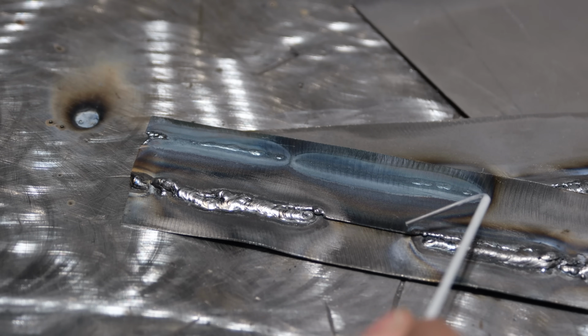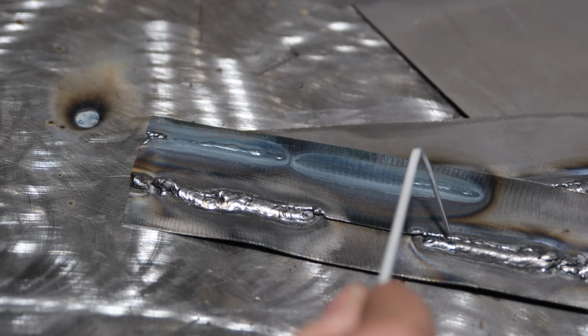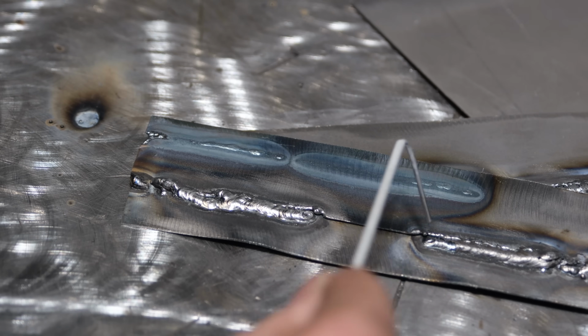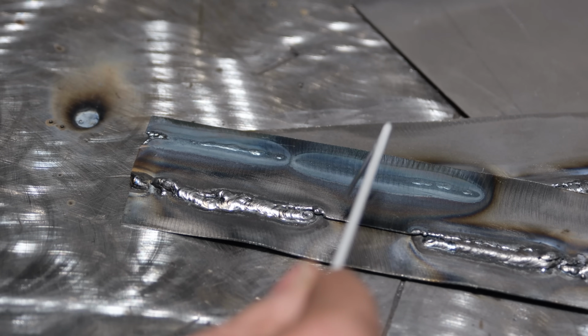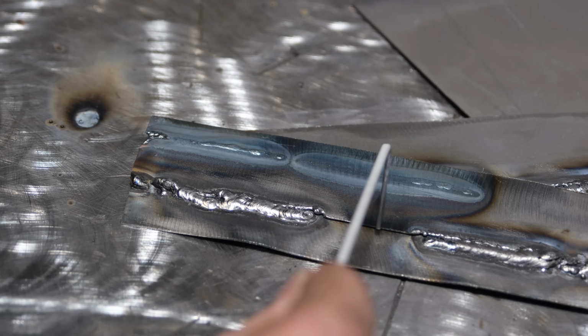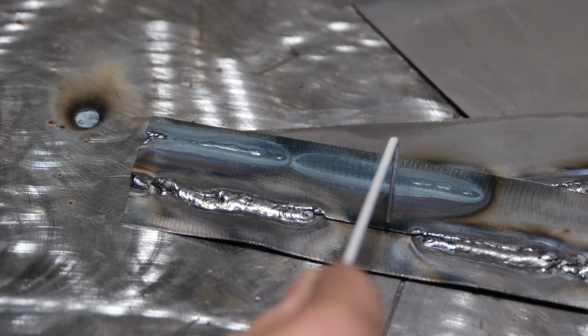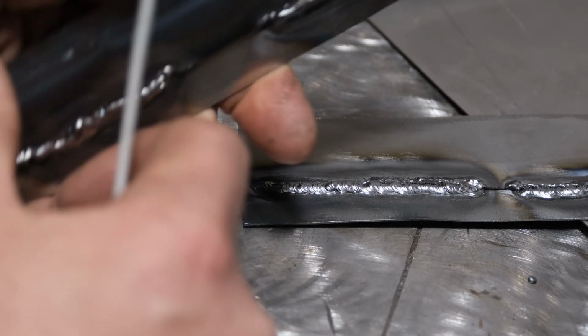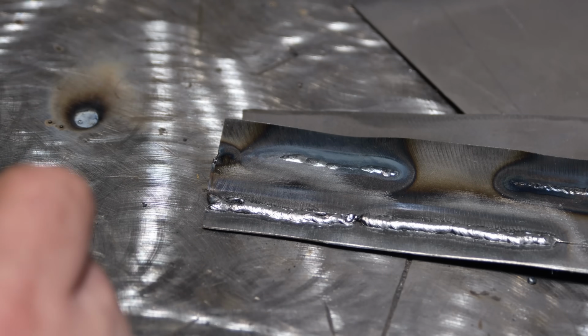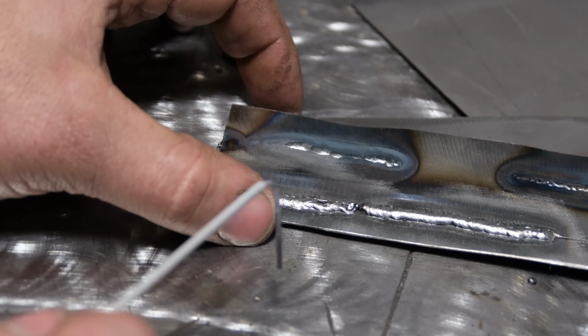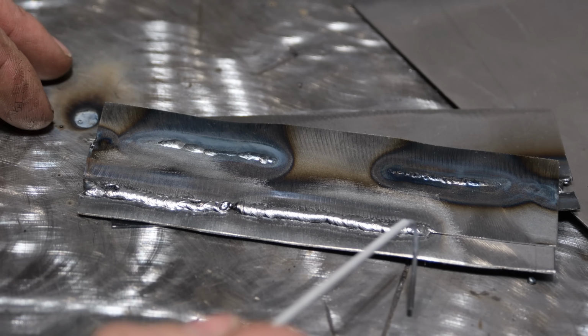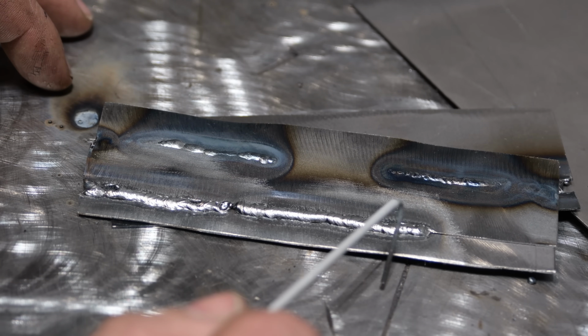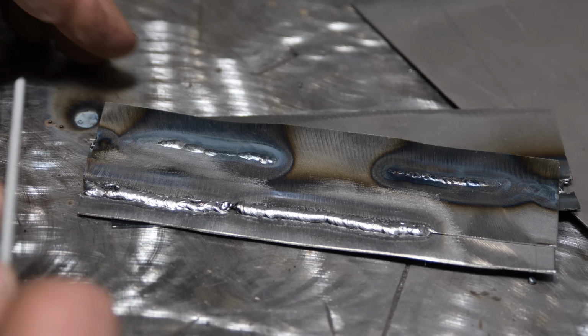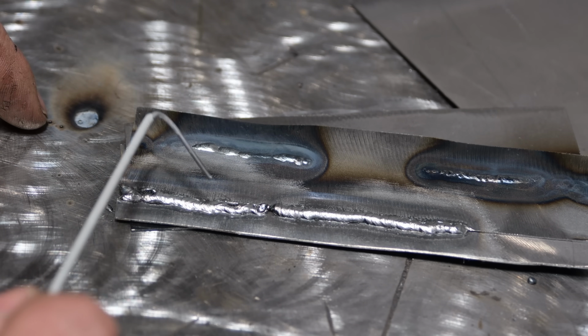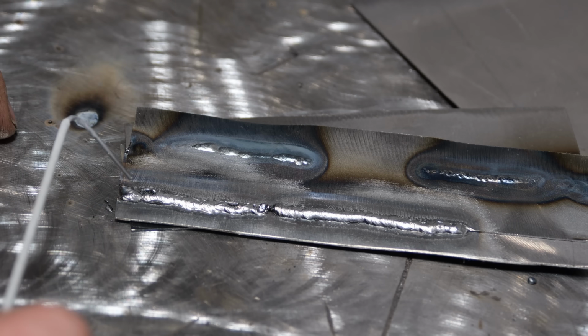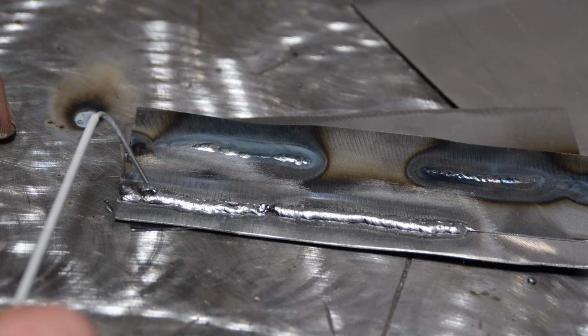So both of these rods under conventional circumstances are pretty tough to get decent results with, because the amperage it takes to stabilize the arc and get things to work well is the amperage it takes to blow through it. It's a real fine edge there. And that's why for the last welds, I pulled a trick out of my sleeve and ran what's known as DC electrode negative. For the previous welds, I did all on DCEP, which is what you normally should run these rods on. By switching to negative polarity for the stinger, you actually reduce penetration significantly.